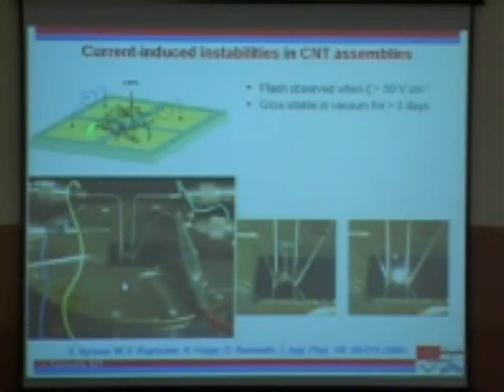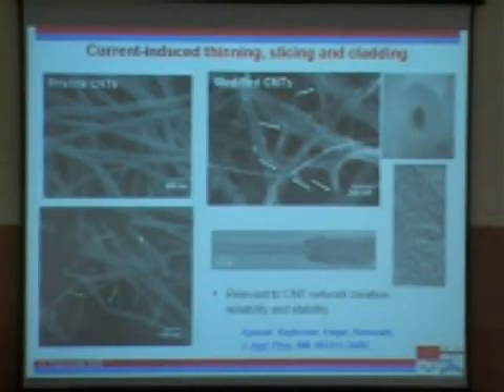You just spread out some carbon nanotubes, with 4 terminals and pass current. And this arcing occurs because of carriers jumping across the overlapping nanotubes. And if you look at the changes that are happening, the changes are very similar to what I showed you in the ion bombardment case. You get cutting and thinning of carbon nanotubes. You also get cladding or welding of tubes and so forth. And this you can do in a very cheap way.